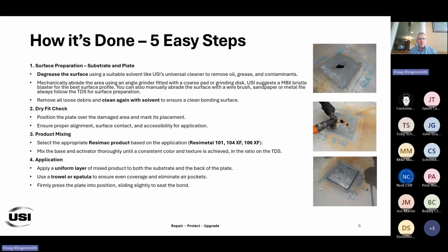You basically want to make sure the product has peaks and valleys to bite into. Usually we're looking for 2.5 to 4 mils. You want to then position the plate over the area, make sure it fits properly, and then you'd mix the product according to your technical data sheets.